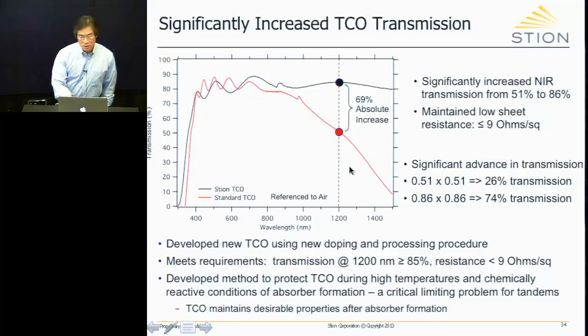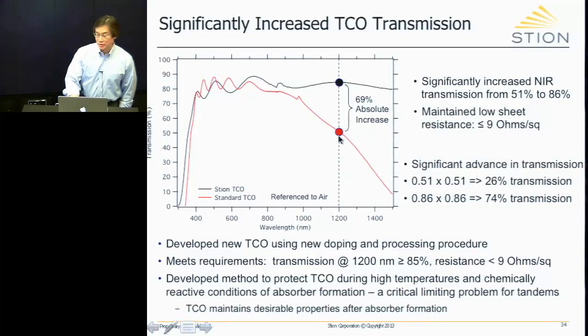So again, if you are at 51% transmission, which is typical for TCOs, you're losing 49% of the light. If you're at 86% for two of them, you're at 74% transmission, which is significantly better, but it's still not great, right? You're losing 26% of the light. But that's enough to get to the high efficiency that we've been able to achieve. So again, we've been able to get to very high transmissions in the near infrared with low resistivities because of the carrier mobility.